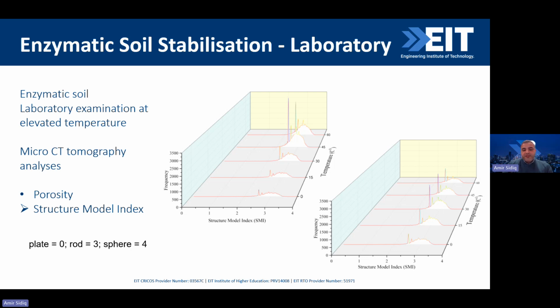But then for the enzymatic material, the frequency is almost constant. And then it's slightly moving toward 3.5, which is going toward the spherical shape. But the actual frequency is almost constant. So we can see again from the different parameters or the shape variations, the enzyme is still actually controlling these voids or the actual clay particle properties.